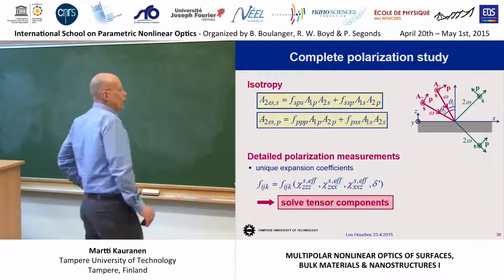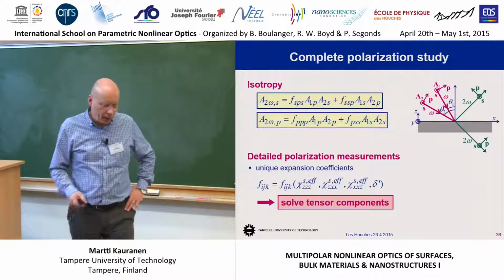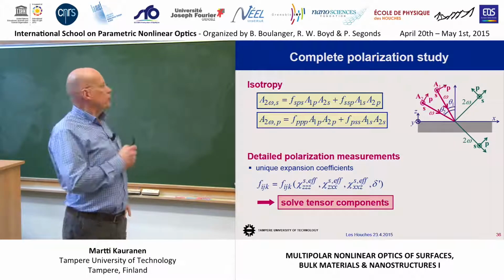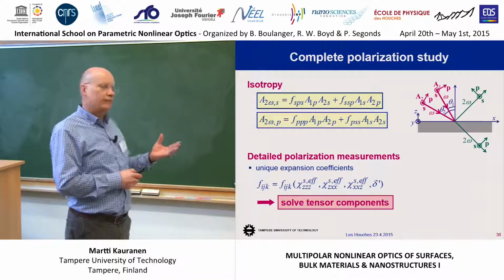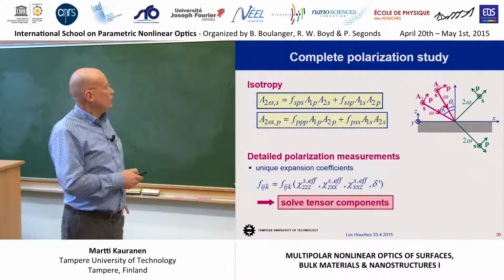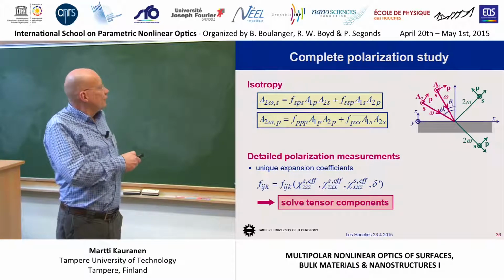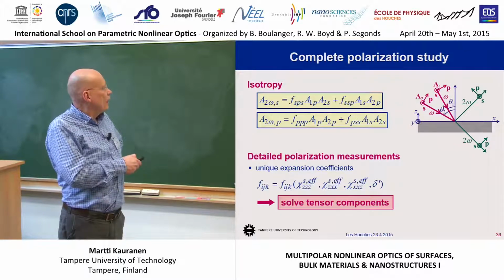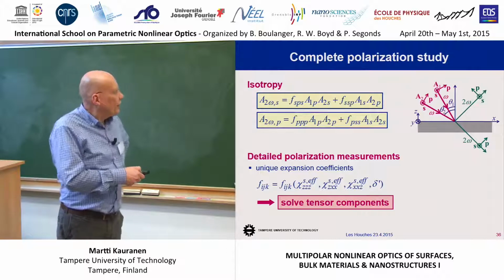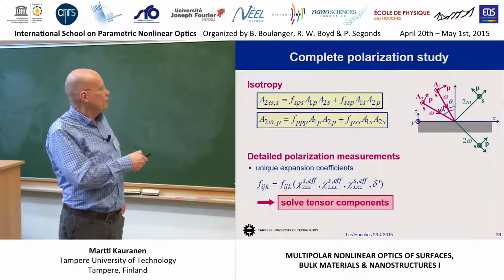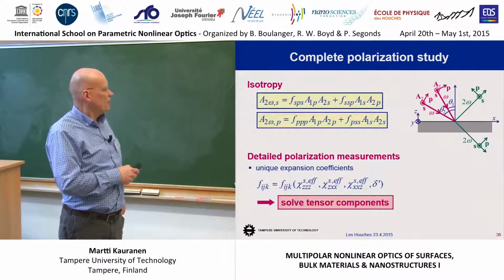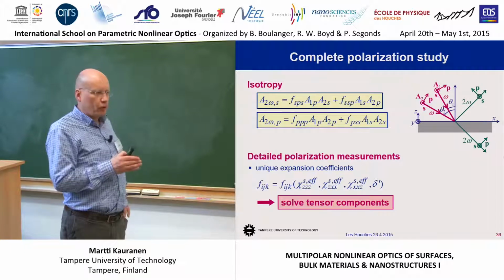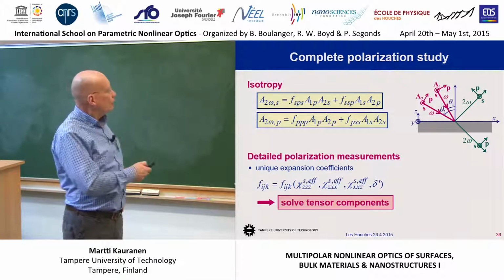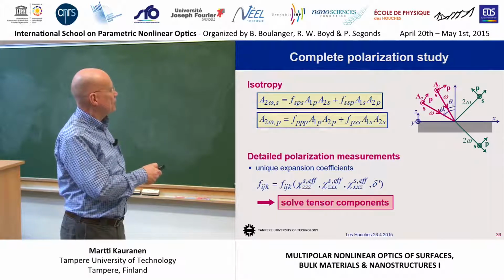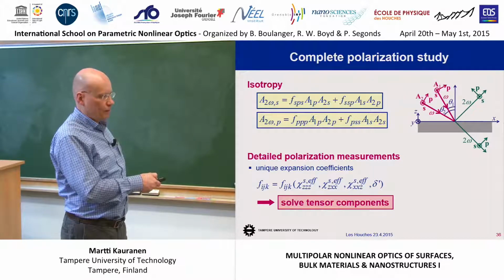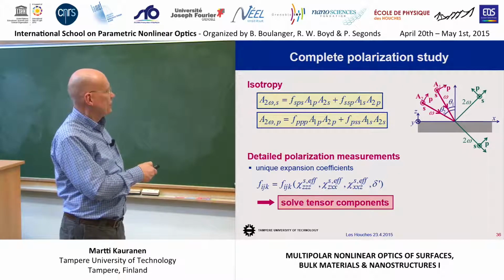Okay, then we can try to do a much more complete polarization study. And the idea is that when we look at the isotropic surface symmetry, the symmetry of the sample for the surface part and the bulk part, it turns out that we can always express the S-polarized signal in this way and the P-polarized signal this way. So in an experiment, we can try to measure these parameters F, which represent coupling of the signal to the P and S components of the fundamental beam. Okay? And the reason that we don't have, let's say, a P-P combination here is because of the symmetry of the sample. But then we have P-P input here in the P-polarized signal and so on.